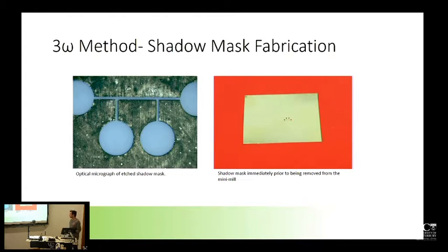So this is what I end up with in the end. This is a piece of brass shim that's 50 micrometers thick, and that's what I get off the machine in the end. I know it's quite hard to see. And over here you can see a microscope image of not exactly the same design, the pads are bigger in this design. You end up with some burring at the edges, which are faithfully represented when you shadow mask it. So you do a weak nitric acid etch and it sort of smooths all the features over without actually affecting the width of the channel as much as a stronger etch would anyway.